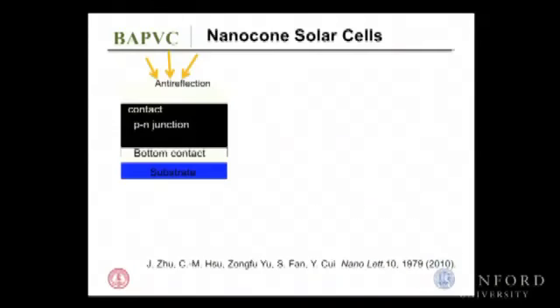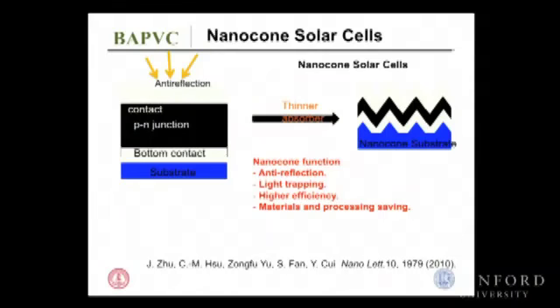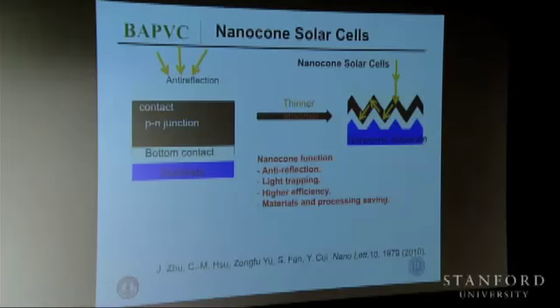So based on this, we also extend this idea to realistic solar cells. We take a substrate, we pattern a nanocone, and deposit the amorphous silicon material on top, forming these nanocone solar cells. Doing it this way, you can couple the light to travel horizontally. Eventually, you only need very thin silicon, amorphous silicon in this case. I will come back to crystalline silicon later. To absorb all the above bandgap photons, you can save materials, you can save processing. It's possible to also improve the efficiency because you concentrate the sunlight into this thin amorphous silicon.